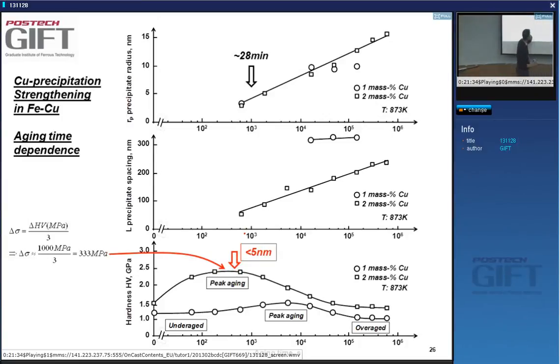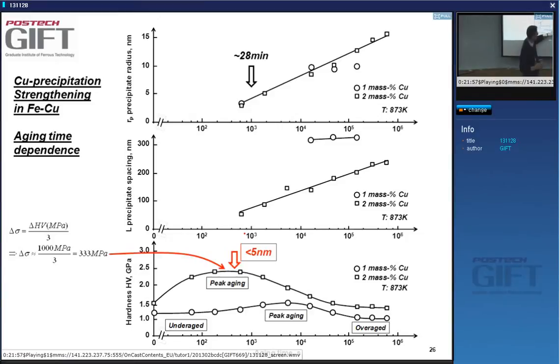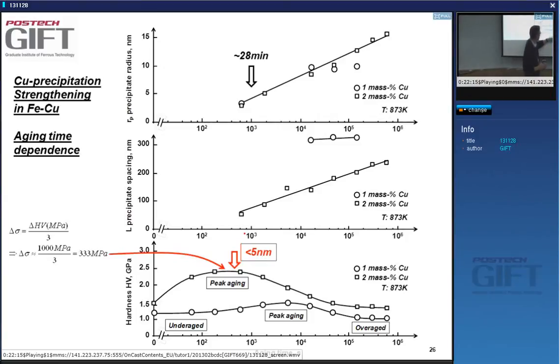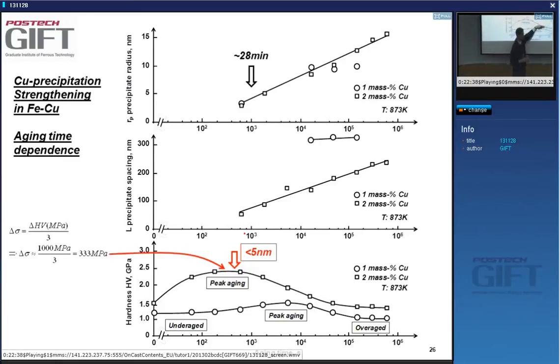At 1% copper there is a peak hardening at about 10,000 seconds. With more copper, peak aging is reached around 400 seconds — a few minutes. Before the peak the material is underaged; after that it is overaged. This transition is classically defined as the transition between particle cutting and particle bypassing, though it doesn't have to be that way.